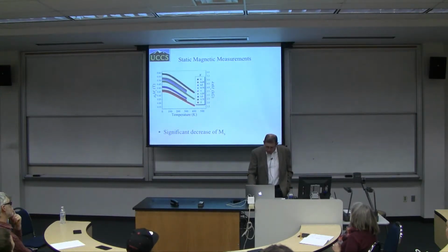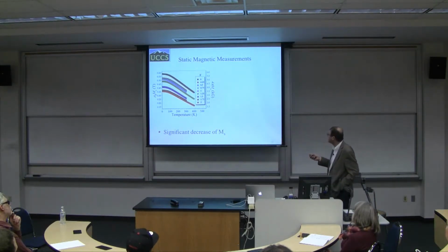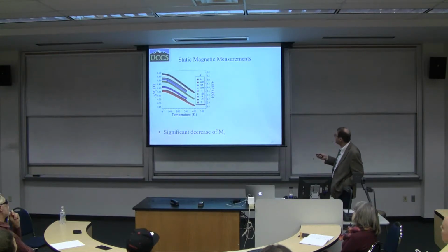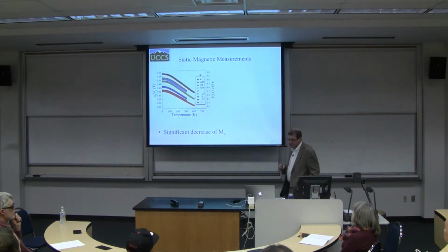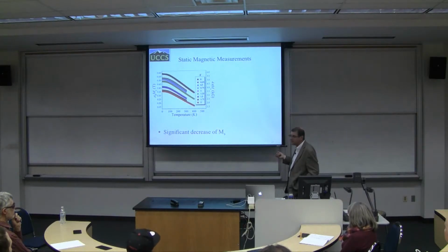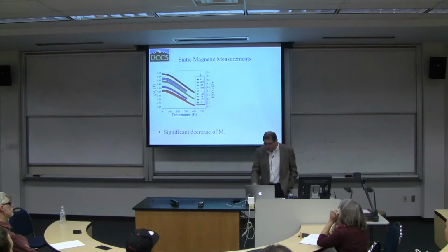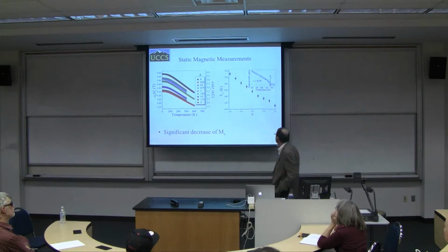So of course we've done all the systematic measurements of this for all the samples, and you can clearly see that initial decrease is very small, up to maybe 75, 80 Kelvin, and then it is basically going linearly down. These measurements were done with the SQUID magnetometer. Actually, all the data which I have shown you so far were done with the SQUID magnetometer. But the SQUID magnetometer, at least the one which we have, can only measure up to 400 Kelvin. So if we want to see what's happening at higher temperature, we have to use VSM.